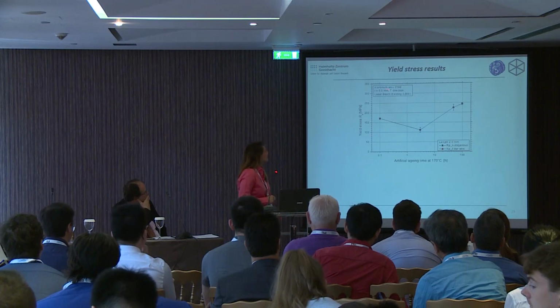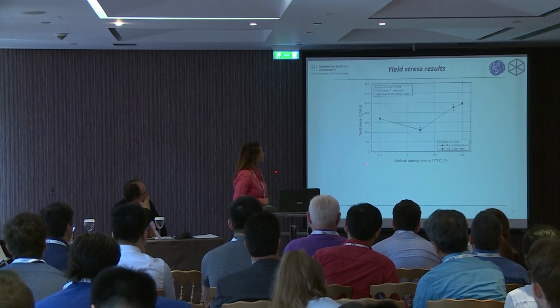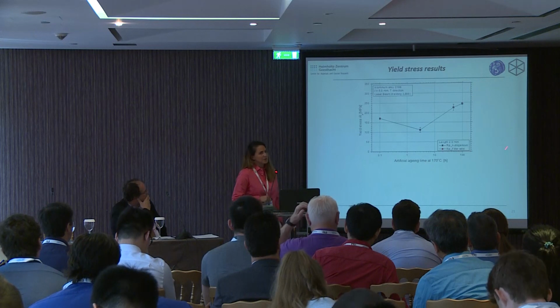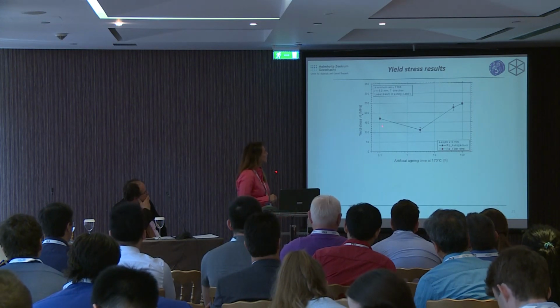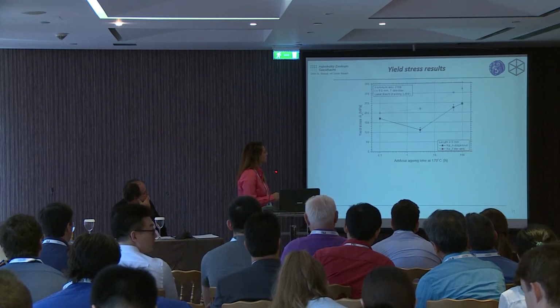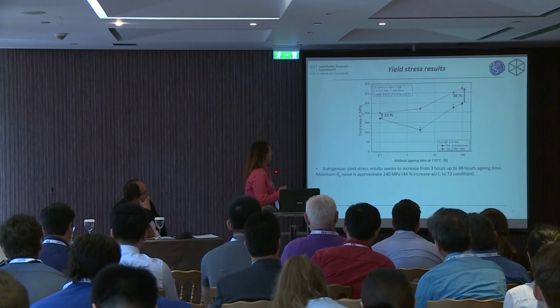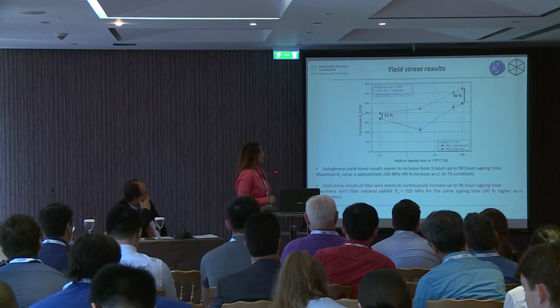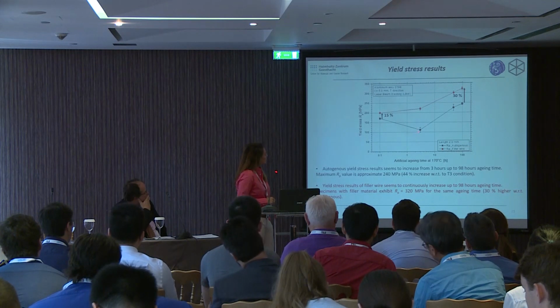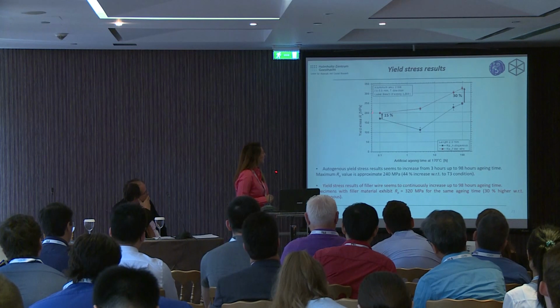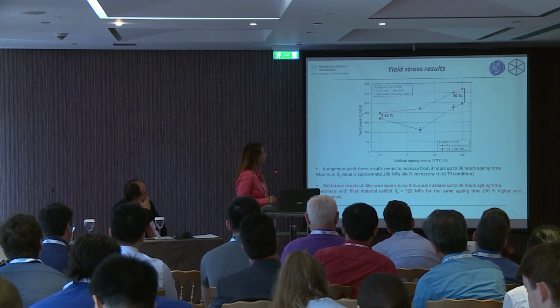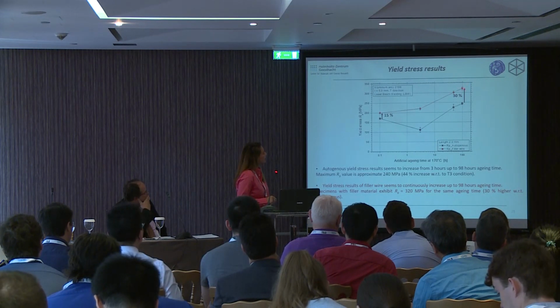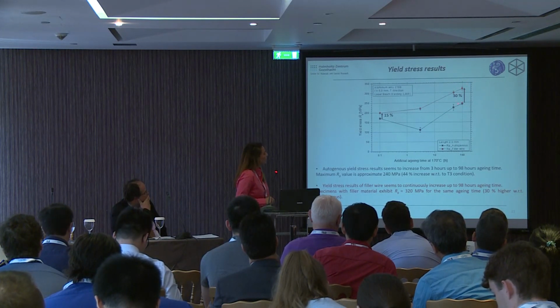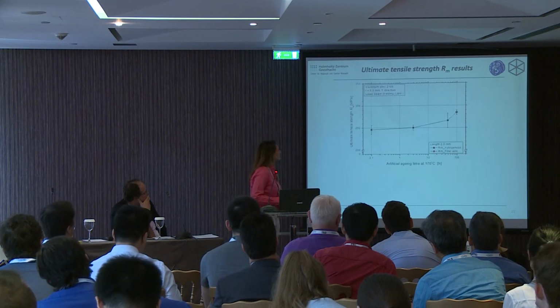Let's sum up the results. So we have yield stress versus artificial aging time at 170 degrees. With black we have autogenous, and with red we have the filler results. Autogenous results seem to increase from T3 up to 98 hours, but for filler wire we have a continuous increase from T3 up to 98 hours, which is 30% higher compared to autogenous.